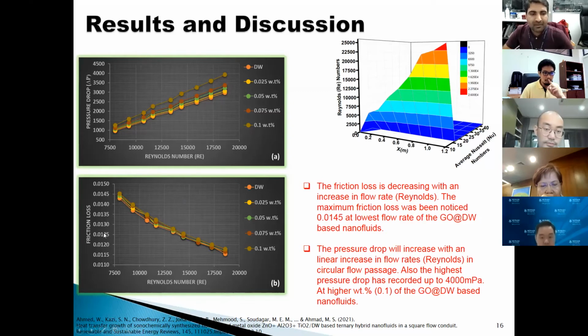On the other hand, the friction loss is vice versa. The friction loss for all the weight concentrations and the distilled water shows that as the flow rate is increasing, the friction loss inside the heat exchanger is going to drop down. So it's showing that the highest friction is 0.0145 at the lowest flow rate, while at the highest flow rate, it's going to drop down.